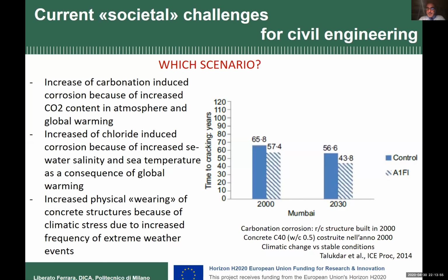And if you see on the same buildings how the service life evolved with time, because climate conditions change, you can see that also for a building built in 2000, after 15 years, because the study then took the data of 2014, the expected service life already reduced by about 10 years, so to about 57 years. And the same, even faster, decrease will occur in the future.